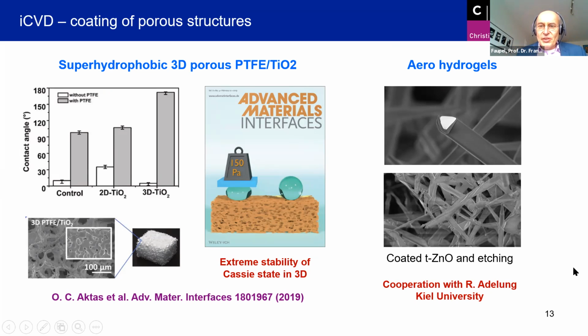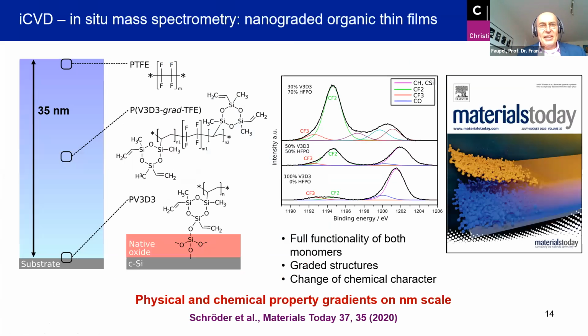We recently, together with Rainer Adelung from Kiel University, also coated his zinc oxide structures. He has zinc oxide network structures. I think many people know his work. And we again make a conformal coating of those structures. And then we etch away the zinc oxide and we get aero hydrogel networks. So these are completely organic hydrogel networks with very interesting applications in biology as scaffolds, for instance. But today I have no time to go into details.